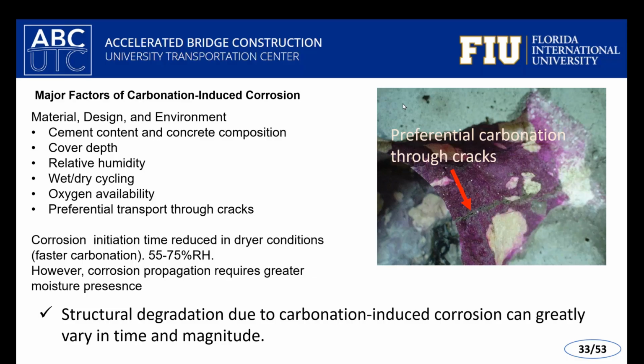This is a picture of the side of a core hole taken from one of our large bridges in Florida, a bridge that was one of the first to use high performance concrete. A chip was taken off the side of the core hole, and a pH indicator spray was used to indicate where carbonation is occurring or not occurring. The phenolphthalein solution is sprayed onto the surface, and when you see purple in the picture, you see where it's not carbonated, as to be expected with this good quality concrete.